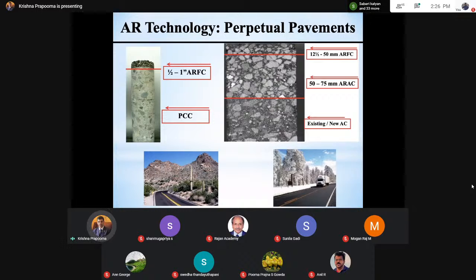There are a few sections in cold countries where I have seen, because I worked in Europe, we placed asphalt rubber there also, and we also saw some cracks. No doubt there are cracks during the winter season, especially the low temperature thermal cracking, but then it started to self-heal. That self-healing capacity is coming from the rubber's resilient property, because rubber is resilient in nature. It's elastic, right? It can come back to its original.